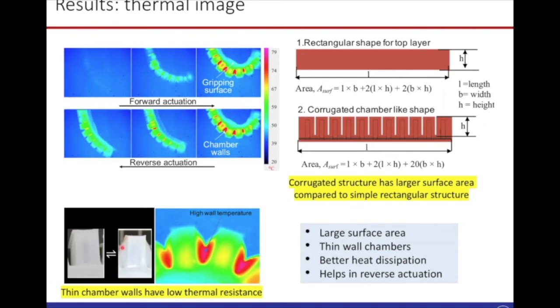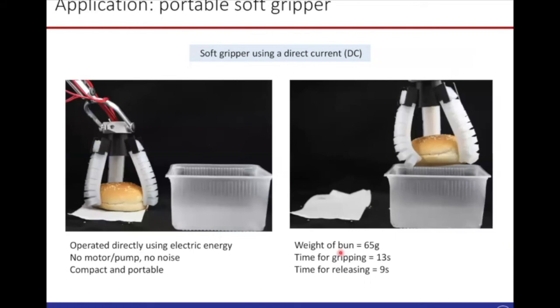Now, the chamber walls are deliberately made thinner. This thin wall will have a lower thermal resistance, which will also help in heat dissipation. So all this large surface area and thin wall chamber should help in better heat dissipation in a reverse actuation. That's why we have a reverse actuation within like 30 seconds, which is not very bad. Now, finally, we show the application of our actuation system. We developed a soft gripper.